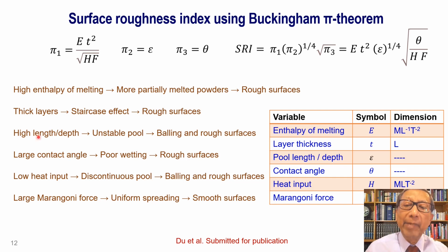When we do a similar exercise, we can make a surface roughness index or SRI, which would depend on E, the enthalpy of melting, the layer thickness T square, the epsilon, which is pool length to depth ratio to the power 1/4, to square root of theta, which is the contact angle. H is heat input per unit length, and F in this case is the Marangoni force.